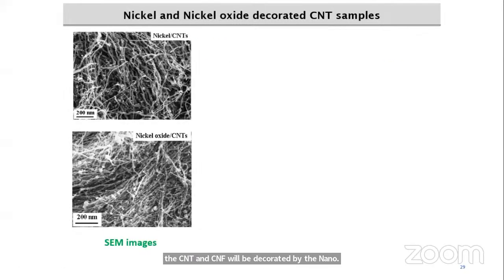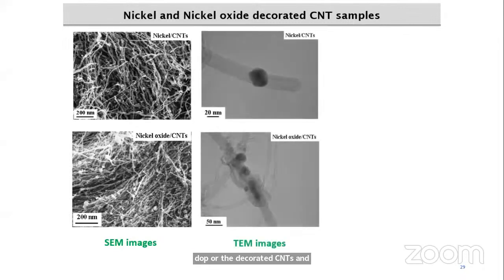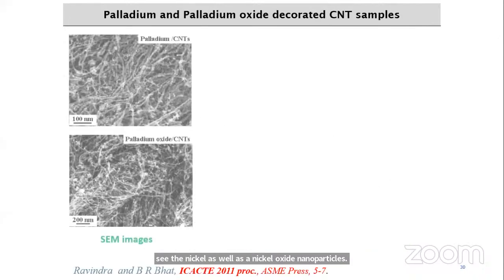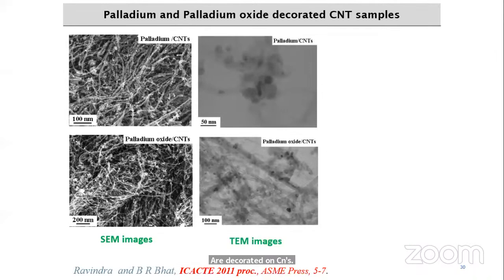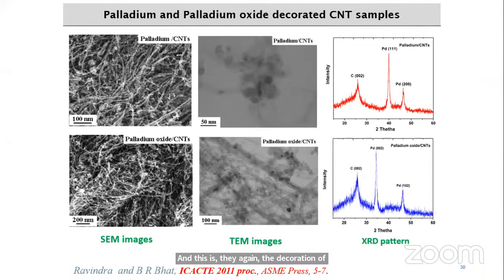Now, these are the nickel-decorated CNTs and nickel oxide-decorated CNTs. And these are the TEM images where you can clearly see the nickel as well as nickel oxide nanoparticles decorated on CNTs. And this is again the decoration of CNT and CNF using palladium, and these are the TEM images for the palladium nanoparticle and palladium oxide nanoparticle